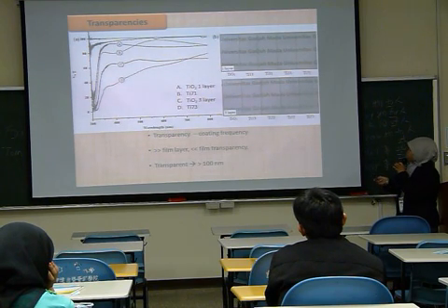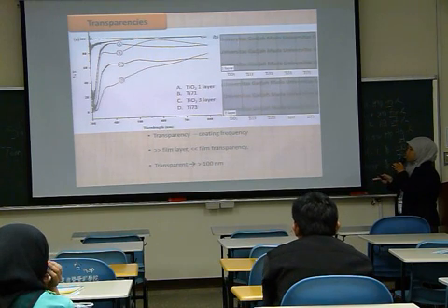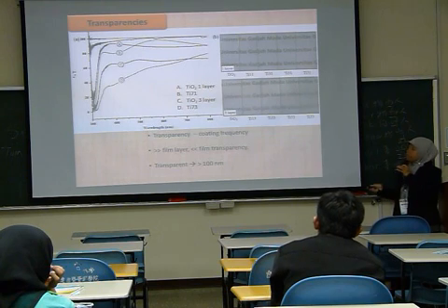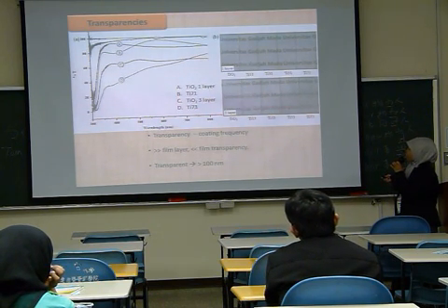And since this layer was transparent, it is proposed that to achieve the transparent hydrophobic film, the thickness of the film should be less than 100 nanometers to achieve this kind of transparent film rather than this rather opaque.